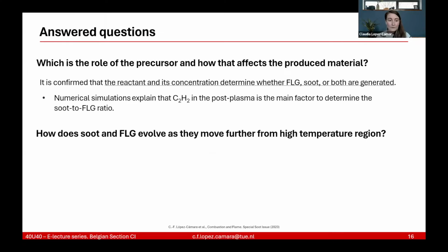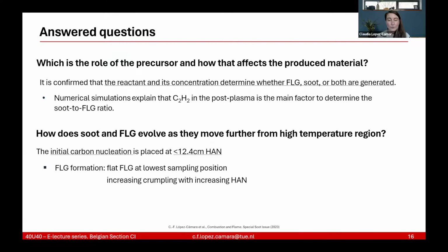Moreover, to the question of how soot and few layer graphene evolve as they move further from the high temperature region, we saw that the initial carbon nucleation is placed below 12.4 centimeters above the nozzle, because at the lowest point of sampling, we already see graphene fully formed and soot formed. Therefore, it should happen even in a lower position. And for graphene, we saw that we did have flat graphene at the lowest sampling position, and it's crumpling as we increase the height above nozzle.